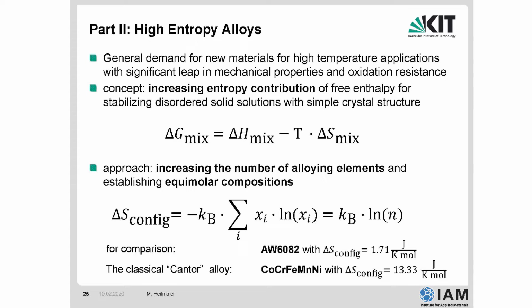And the mixing entropy can be influenced strongly by what we call the configurational entropy. Configurational entropy means taking different atoms in different concentrations and putting them randomly on lattice sites in the crystal. And this is the simple formula. I don't need to explain it. So the configurational entropy actually scales with the Boltzmann constant and with the number of alloying elements, right? So just a simple comparison, a classical aluminum alloy 6082, as some of you may know, has a configurational entropy of 1.7 joule per Kelvin per mole. And what we call the classical Cantor alloy, this is a 5-component alloy in equal compositions, chromium, cobalt, iron, manganese, nickel, has a configurational entropy of 13 joule per Kelvin per mole instead of 1.7, so a factor of 10 higher. Now let's see how this concept works.